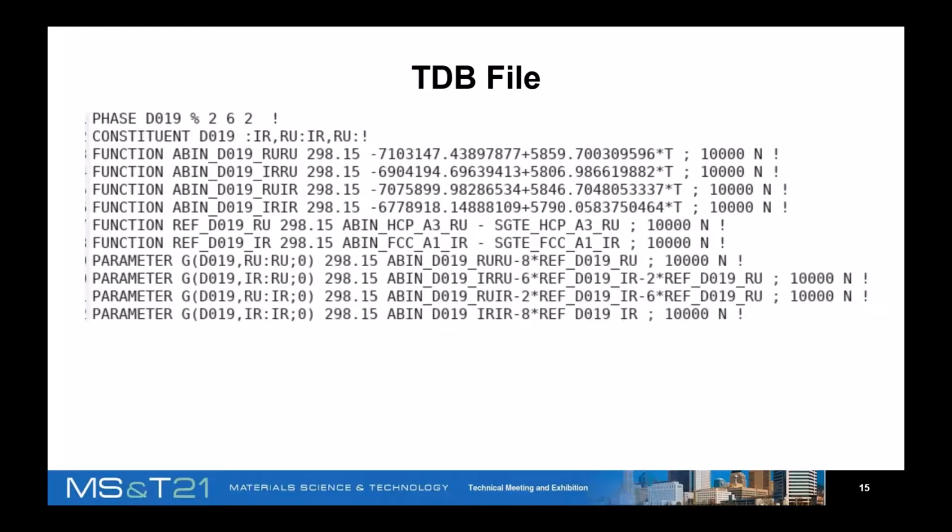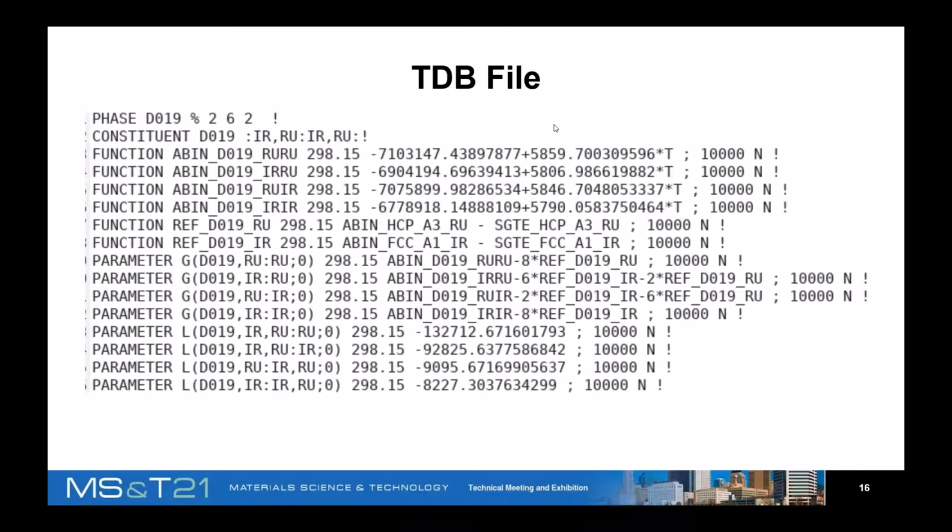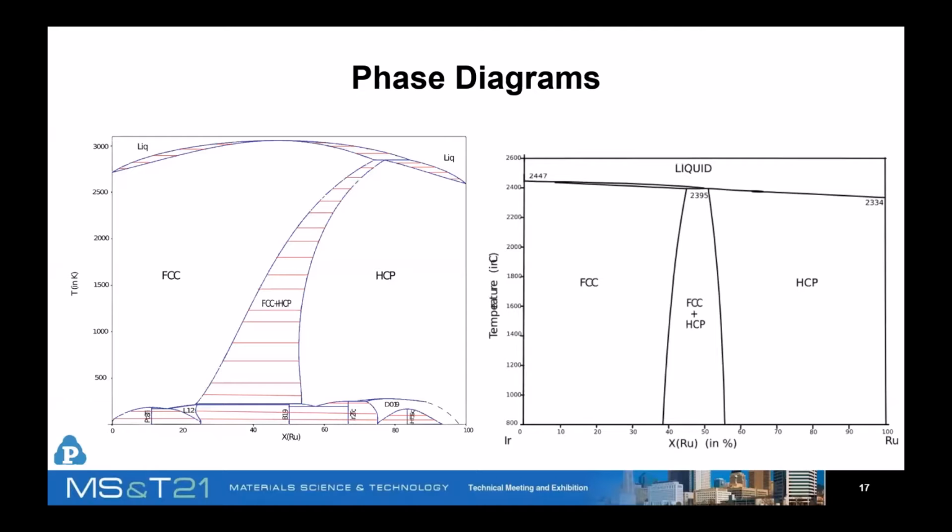And finally, the free energy of the end members is then the difference between the formation energy of the end member and the reference energy of the individual constituents. Last but not the least, we add the excess free energy functions. We don't show it here, but as mentioned before, as a final step, we combine this energy data for each phase along with the SGTE energies to create a TDB file that can then be used to calculate phase diagrams and other equilibrium phases downstream tasks mandate.